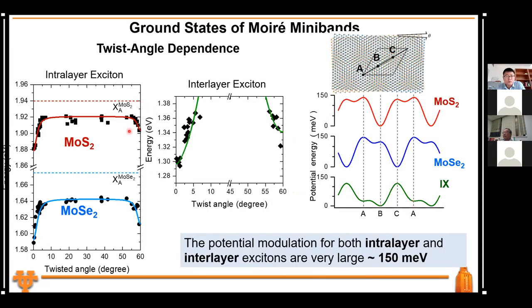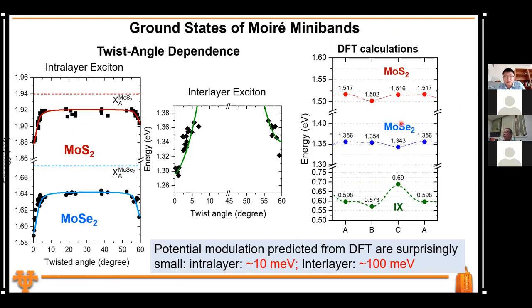Now if you plot them as a function of twist angle, this is for the MoSe2 intralayer exciton, this is for the interlayer exciton. Then you can try to come up with a model, with a moiré potential and its amplitude. If you use this, you find out you need to fit the moiré potential depth at around 100 to 150 meV in order to fit the data. Now, if you take the DFT calculation, the interlayer moiré potential is indeed about 100 meV. So, you know, in our 2017 paper, we already compared that.